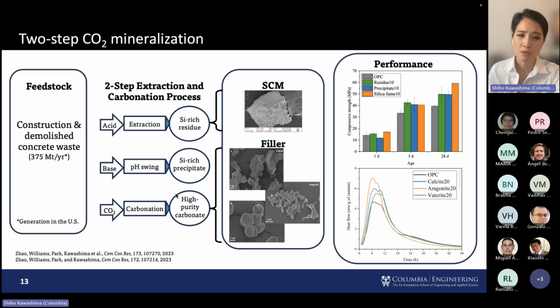And just as a note, we focus on the two-step extraction and carbonation process, but there are also direct processes, where you just bubble CO2 directly, or the dry method, which would be subjecting your powder to an accelerated CO2 condition and controlling the relative humidity, relatively high humidity. In that case, you get a single product where the carbonates and the silicate co-produce. So you get this one product, but you still get the carbonate, and you're still left with a pretty reactive pozzolanic material. So one step, you get one product. Two step, you get two separate products. It really depends. There are pros and cons in both. Obviously, the direct process is much more straightforward. It's one step. But in the two step, you get these two materials with higher purity.